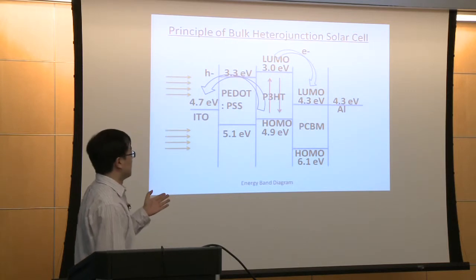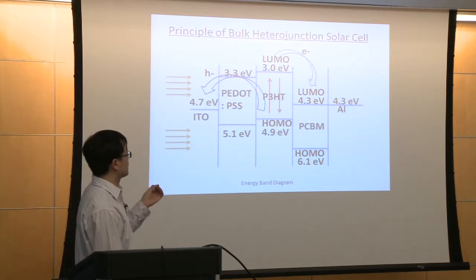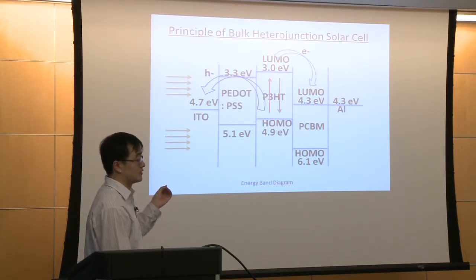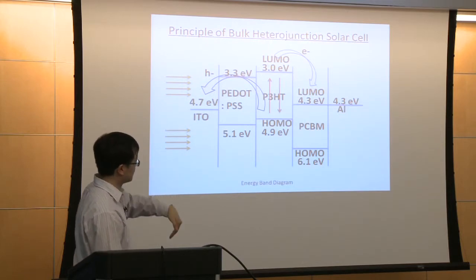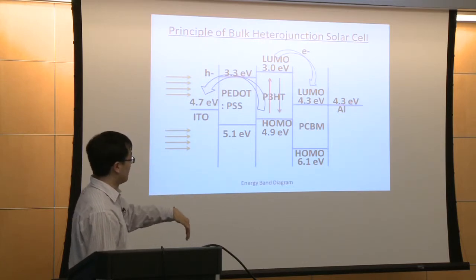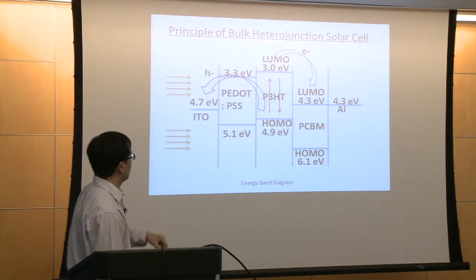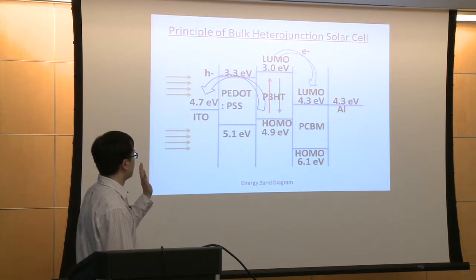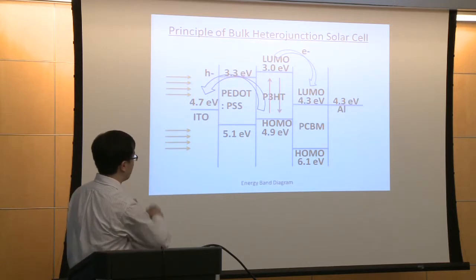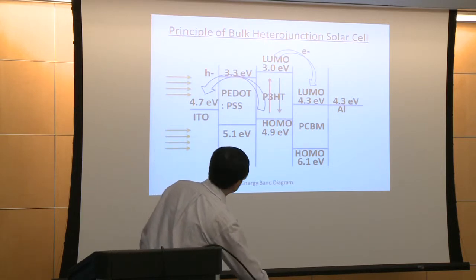Because the conduction band of PCBM is lower than the conduction band of the P3HT, the electrons can easily jump over to the PCBM conduction band. And the holes will jump through the PEDOT:PSS back to the ITO electrode.